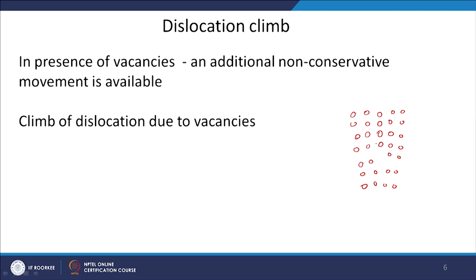Dislocation climb can happen only when you are at sufficiently high temperature where the equilibrium vacancy concentration is of a certain amount — only then will it be an effective process. Both creation of vacancies and diffusion of vacancies require high temperature for this climbing process to work. You have dislocation generation due to deformation and dislocation recovery through climbing. This climbing process also helps in rearrangement of dislocations, and as mentioned, this rearrangement can develop a small low angle grain boundary.